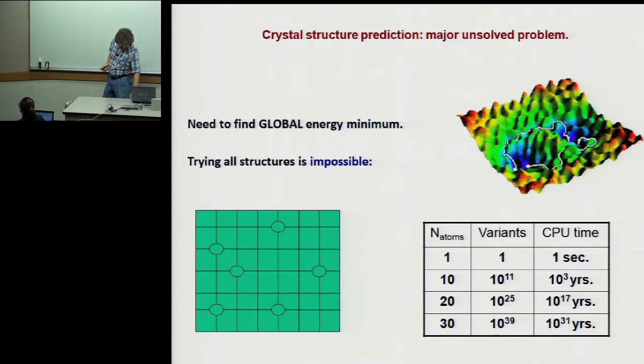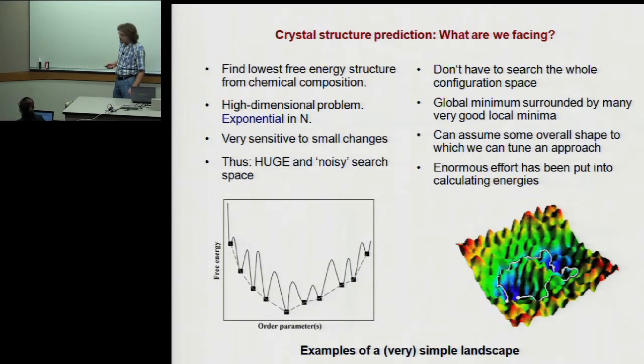And one of the key features of our method and all current methods that deal with crystal structure prediction is local optimization. The search space, for example the energy surface, is extremely noisy and huge. However, we can sort of smooth it and reduce the effective number of degrees of freedom by a lot if we do a local optimization.